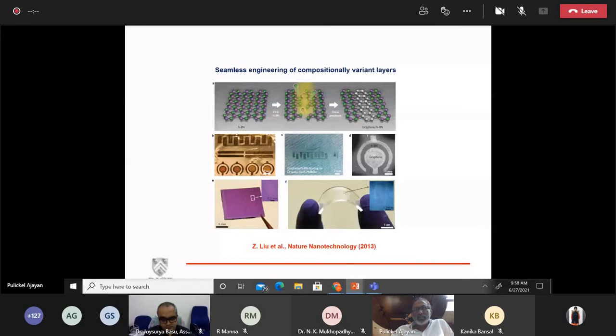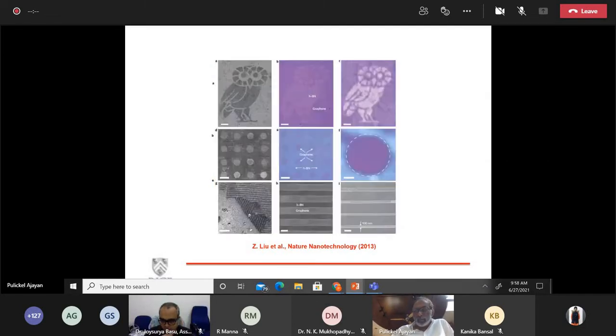For example, if you can stitch together some graphene within the hexagonal boron nitride matrix, you can create these two-dimensional antennas, which are, again, quite fascinating because you can essentially peel off this layer and put it on top of any other substrate. And you can make many patterns within the 2D. So this is kind of the ultimate nanoscale engineering you can do, and this being a 2D platform.